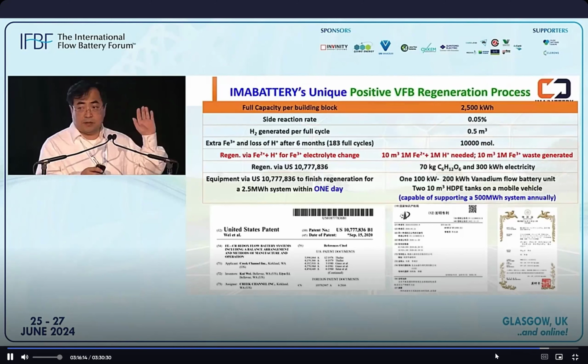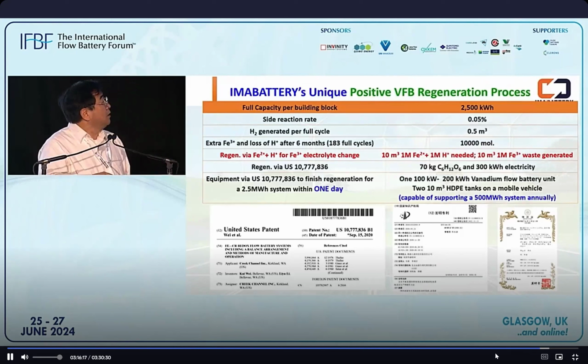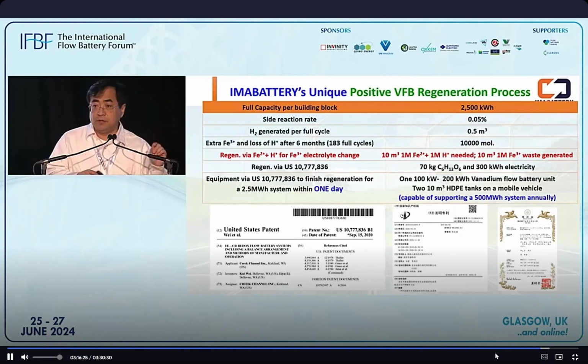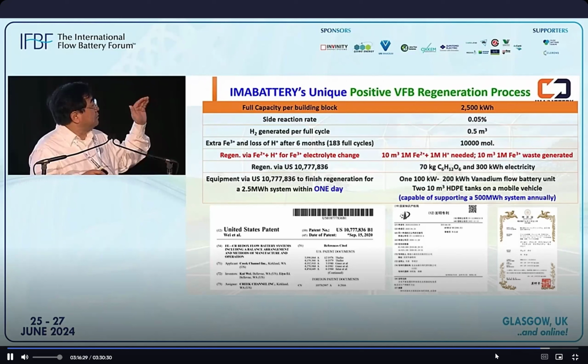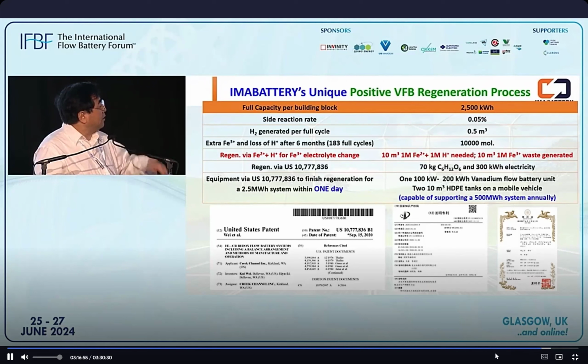So with this nitrogen containing complex, we can reduce the hydrogen generation rate from about 1% in the original traditional system to 0.05%. So the hydrogen generation is largely reduced, but it's still too much for a large system to be sustainably operational in the long term. Say, for example, for a 2.5 megawatt hour system, if we run every half year, we need about 10 cubic meters of iron 2 and proton electrolyte to regenerate this hydrogen-related iron 3, and then we make another 10 cubic meters of iron 3 electrolyte waste. So that seems like still too much.